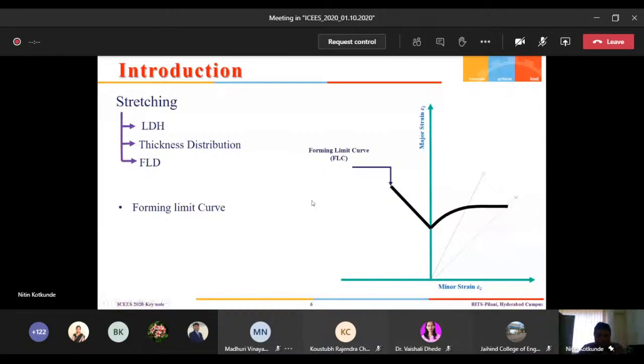The solid dark line which you are seeing in this diagram is called the forming limit curve, which is plotted as major strain versus minor strain. Surface strain is measured on a formed component at different regions, because we have to do the test at uniaxial, plane strain, and biaxial conditions to get this continuous line. Below this line is usually called the safe limit, and above this line the material is unable to form. The material tears off or fractures, so any kind of failure may happen above this line.